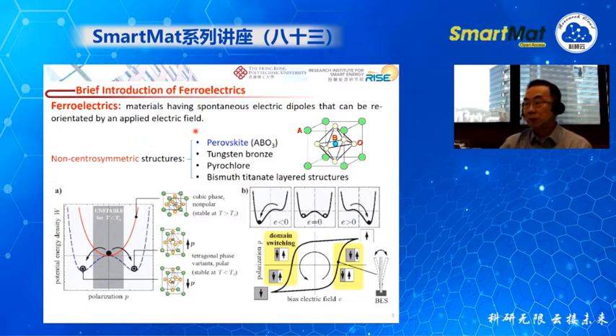A ferroelectric is a material that has a spontaneous polarization, and that spontaneous polarization can be reoriented by an applied external field. Ferroelectric materials normally have a non-centrosymmetric structure. Nowadays, we have four main groups of such structures: perovskite, tungsten bronze, pyrochlore, and bismuth titanate layered structure. Today, I will mainly focus on the perovskite structure, which has a chemical formula of ABO3. Here, the A atom is located on the corner of a unit cell, B is at the center of the cubic unit cell, and oxygen is at the six face centers.